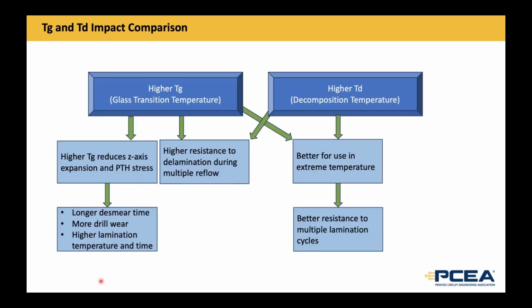What I also wanted to do was, because I used to confuse myself with the TG and the TD, do a comparison and see what similar impact they have on the design and manufacturing, and what differences they have. So a couple of similarities. If the material has higher TG and higher TD, the material will have higher resistance to delamination during multiple reflow cycles. And also these materials will survive better in extreme temperature environments such as automotive applications. So better for use in extreme temperatures. This also means that higher TD materials are going to have better resistance to multiple lamination cycles.